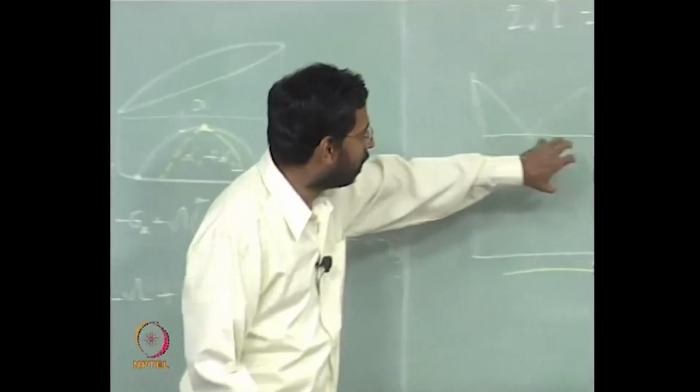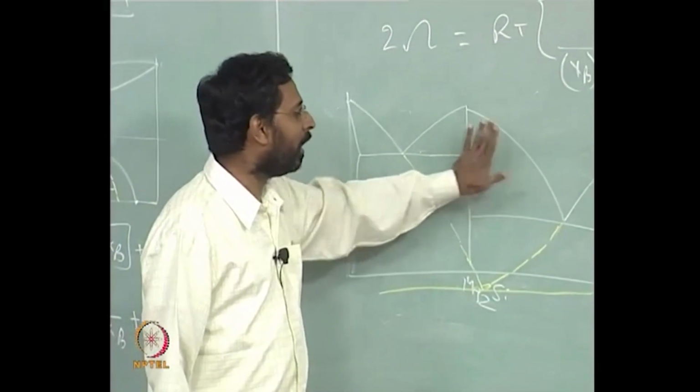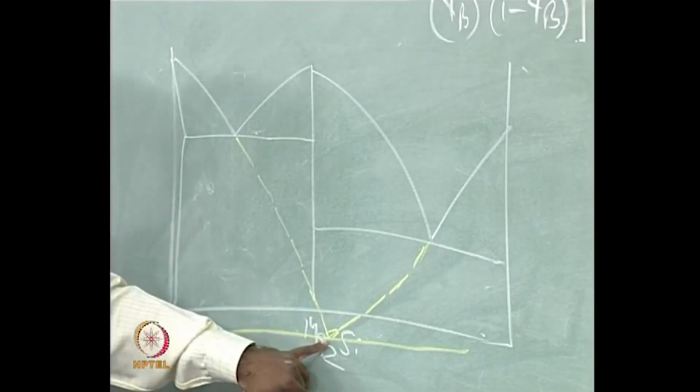But if you see things like this, if you start thinking that this is not forming, what is then going to form? That liquid at that particular composition is going to be undercooled continuously until you reach this temperature. And so that means in this alloy, though the two eutectics are shallow eutectics, still this particular phase diagram can give you a glass.